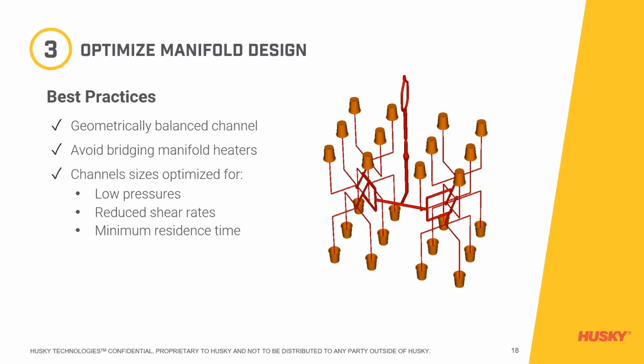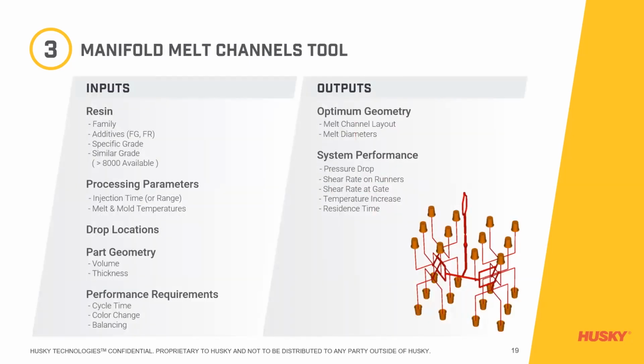Melt channel size optimized for low pressure, reduce shear rates, and minimize the residence time. This is something that the hot runner suppliers, we balance on every system that we build, trying to manage the pressure drop in the system, especially with bioresins, because of the viscosity, it has a tendency to lose a lot of pressure in the hot runner. So we want to take that into consideration. We want to make sure we have an optimal shear rate, so we're flushing those channels every shot. And we want to minimize residence time because of the thermal sensitivity of a lot of these resins in the industry today. Husky engineers each manifold designed for the specific application and optimizes a balance between pressure drop, shear rate, and residence time.